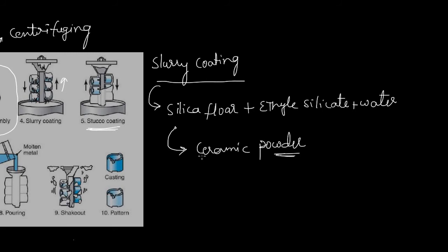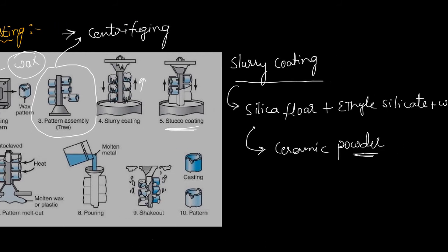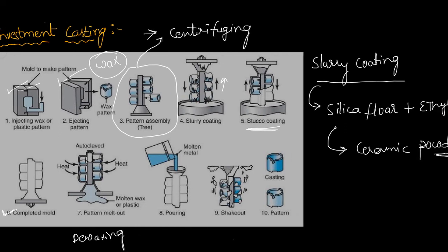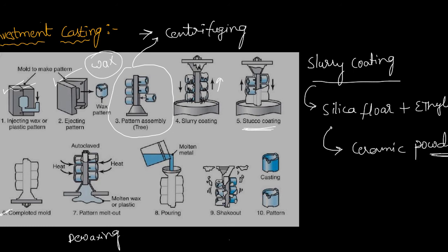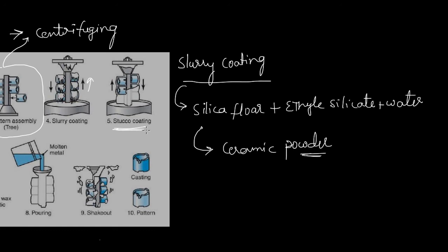The pattern material is wax — candle wax. A fine-grained ceramic powder covers the pattern assembly and forms a shell. After the mold is prepared, de-waxing is done — de-waxing is the removal of the wax pattern by heating the ceramic shell. This creates the cavity within the shell, into which we pour the molten metal directly. After solidification, we break the shell and get our required casting. The slurry plus ceramic powder coating is also called stucco coating, and the process is called stuccoing.